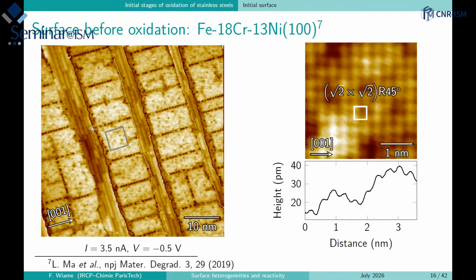On the terraces, we have a surface which is reconstructed, which is root 2 by root 2 rotated by 45 degrees reconstructed. We can see here the profile, the atomic resolution, and you can also see some changes in the height, which are larger than the atomic variation, which are in fact related to electronic effects at larger distance on the surface.